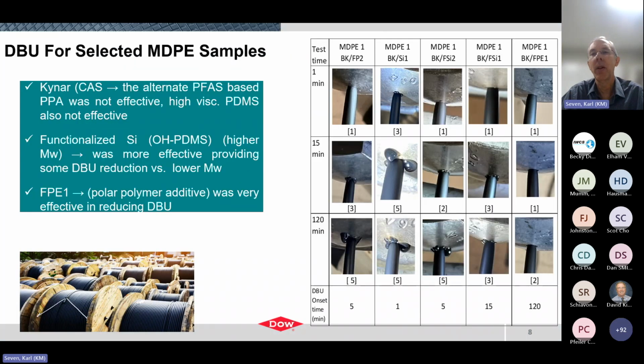Okay, so here now I'm showing die buildup results for some of the non-PFAS-based processing aids that were studied. The first series of pictures in the table on the right here is an alternate fluoropolymer, FP2, that we looked at, and as can be seen in the series of pictures, this shows very poor performance. And so this highlights that not all of these, even the fluoropolymer-based processing aids, can address the die buildup or have an effect on die buildup. And so going back to what I said earlier, depending on the system, the compound itself, not all processing aids can solve or provide every benefit that is necessarily claimed.